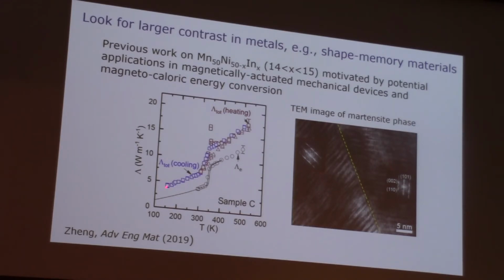At this temperature. If we measure the electrical conductivity and use the Wiedemann-Franz law, the electronic thermal conductivity you can see is basically most of that change. So the lattice vibrations don't seem to play much of a role. The electronic heat conduction increases at the transition and produces most of that change. It's a complicated material. This is a TEM image of the room temperature martensite phase. There's all kinds of nanoscale twinning and stuff going on in there. We're really not sure what that does exactly to the transport properties.